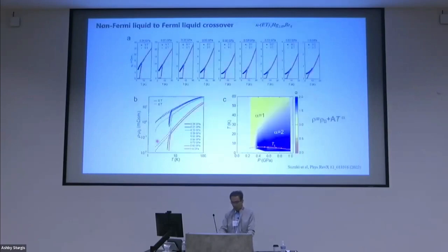maybe realized. Okay, this is the pressure dependence of the resistive behavior. Low pressure and then high pressure. In the low pressure range, the resistivity is proportional to T. But the Fermi liquid behavior appears close to the T-squared temperature dependence here. This is the contour plot of the exponent, and it is unity here in this region, so non-Fermi liquid here, and then Fermi liquid appears, and this crossover is very sharp. In this very low pressure range, we cannot acquire reliable resistivity data because in this material we encounter micro-cracking at low pressure, so we cannot obtain it.